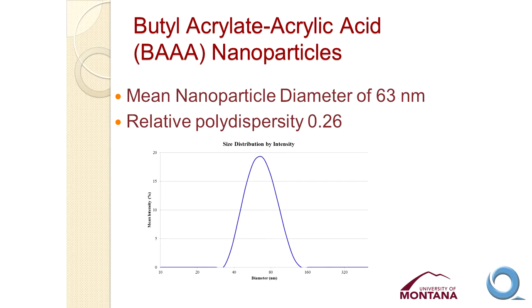After we then go on and do the second step and polymerize the hydrophobic block and form the nanoparticles, we can characterize them by light scattering, and we can see this nanoparticle has an average diameter of 63 nanometers, plus or minus 26%. That's relatively monodisperse for this type of system. Obviously there's some dispersity here, but these are rather monodisperse systems in the end.